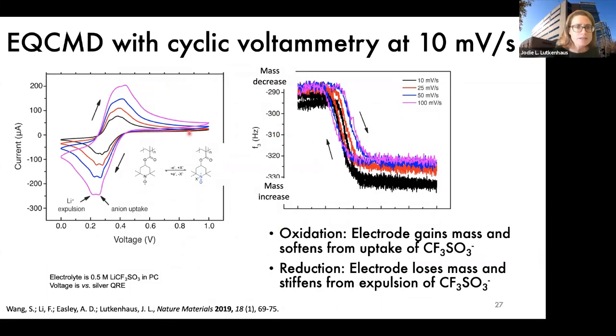And I just want to note that there are some interesting features. You can see these little bumps, or it looks like a few peaks overlaying each other. We've seen this before and other people have in the past, but at the time we were kind of ignoring it, thinking, oh, that's some unexplainable feature, but they kept appearing. And as we went through the analysis, as you'll see, there's actually a real physical meaning for those peaks. There's still the reduction and oxidation of the nitroxide radical, but those peaks manifest from different modes of ion transport in the polymer, whether a lithium is participating or whether an anion is participating.